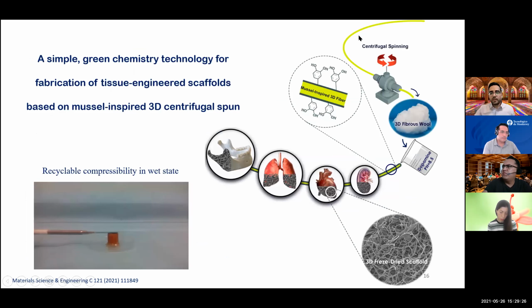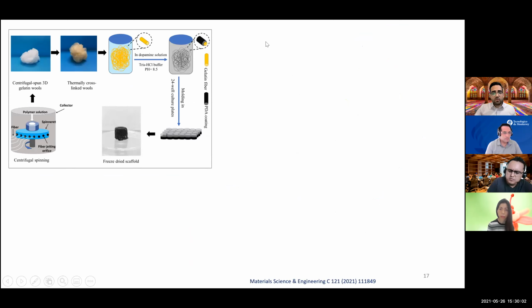And you can see here, we tried to use this centrifugal spinning to produce some gelatin fibrous wool, and after that we used polydopamine to make a thin layer on the surface of those wools, and after that we produced a scaffold. According to this short video, as you can see here, it has recyclable compressibility in the wet situation, and it can tolerate the pressure and again retain the primary structure, and it's really good.